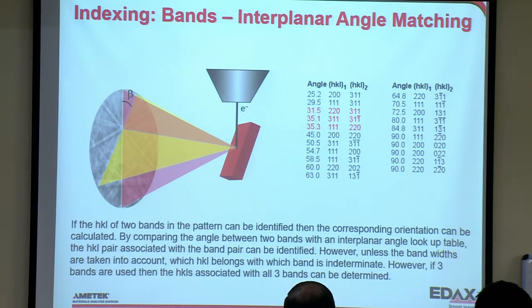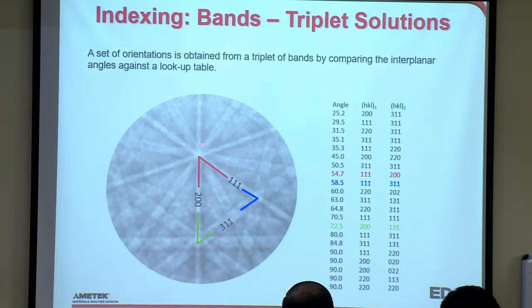That part we don't know yet. But if we use what we call triplets, then we can do that. So for example, if this red triplet here is a 54.7, that means this is a 200 and that's a 111, or vice versa. But if we throw in this one here at 58.5, we know this has to be a 111 because those two match.